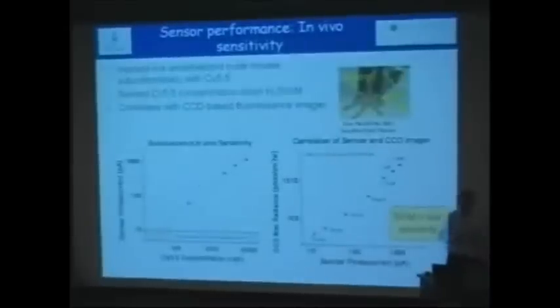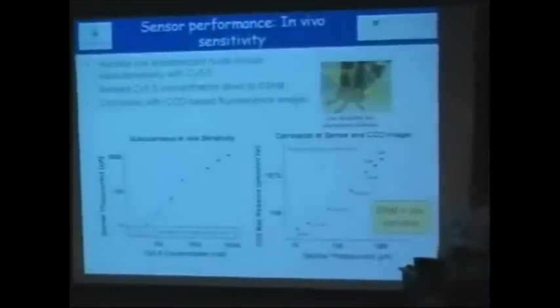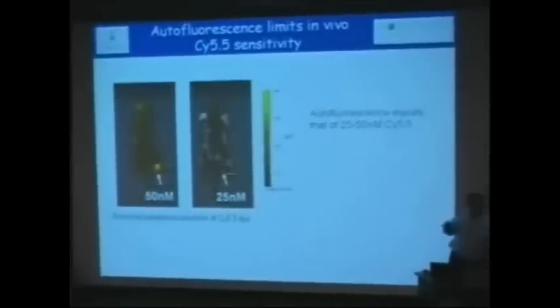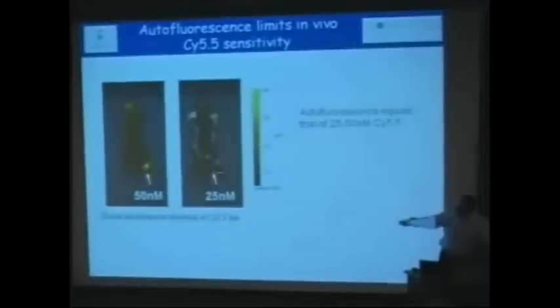We thought this is good, because it is always good to be at a point where you're not limited by the technology, you're really limited by the biology. So we went ahead and did some comparative studies, and this is what you see in a picture from that CCD-based system I was telling you about, IVIS. What you see here is a glowing mouse due to autofluorescence. On the back side, we injected a small amount of dye, and that allows us to know the sensitivity.